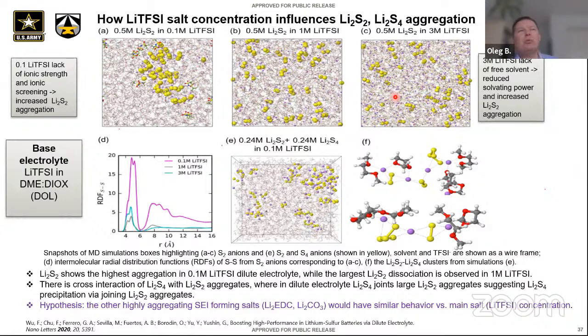I've seen a nice study, for example, from Artem Baskin on how temperature affects the relative stability of solvents. That goes in the direction you're pointing to, because it captures the entropic TS effect on the stability of different complexes. What I can say is that typically the higher the temperature, the higher the aggregation rate. In polymers that often leads to salting out at very high temperatures for polymer electrolytes. That's probably the closest. One of the challenges in the battery area is that there are so many fundamental questions, but also a great need for empirical progress with simple systems. So I'm trying to balance it in our group, which is an army that is very small.